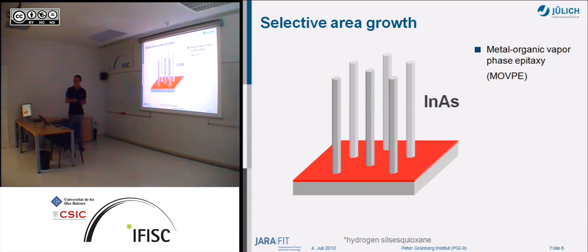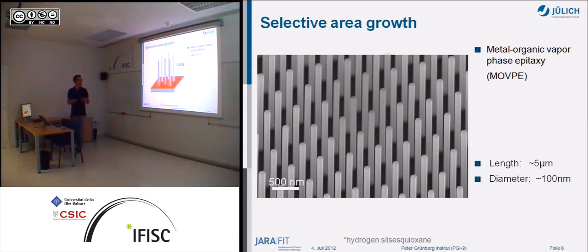So that's a special technique. By that technique you can determine where the nanowires grow, in contrast to most other methods. Here we can really determine where the wires are growing, and we know exactly the position. At the end it looks like this, so you see a very regular field of nanowires.